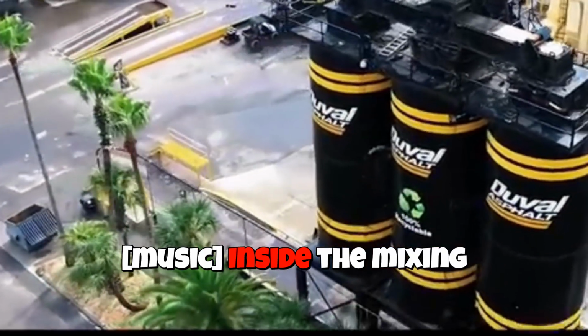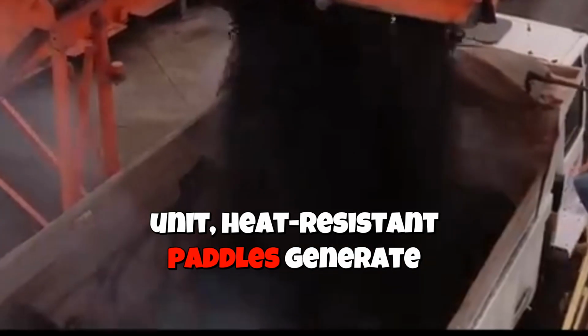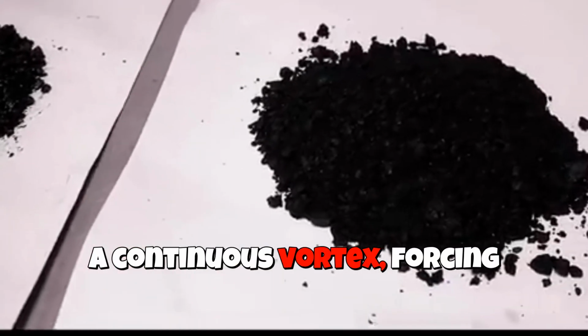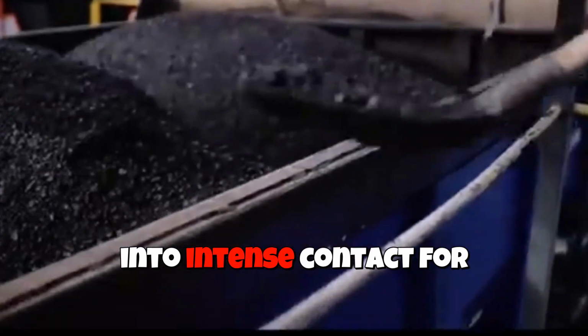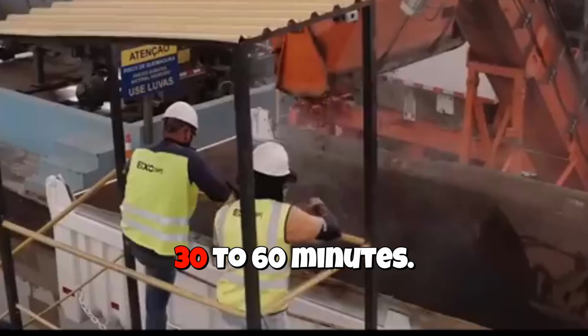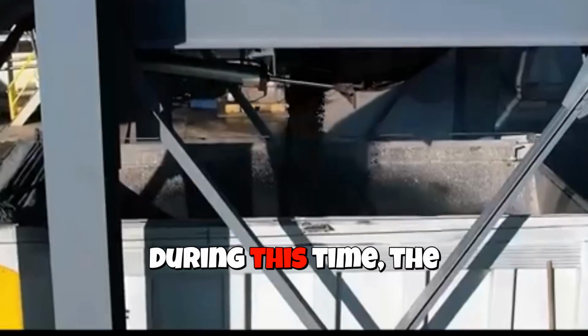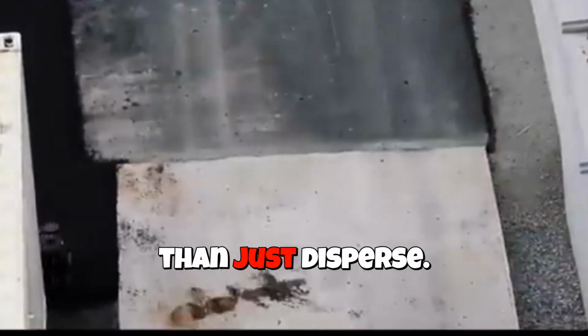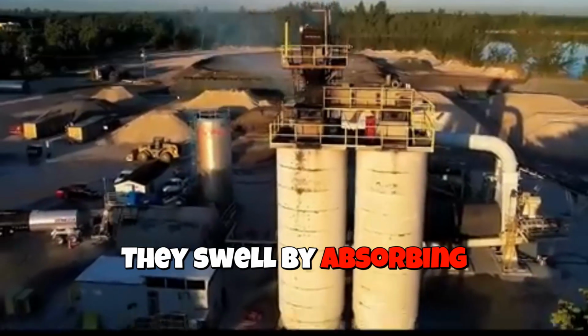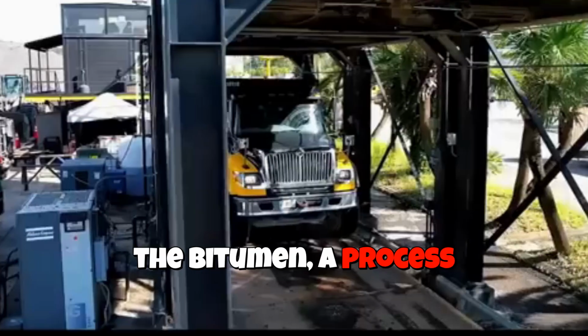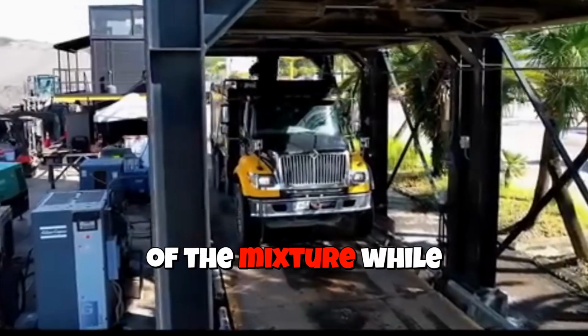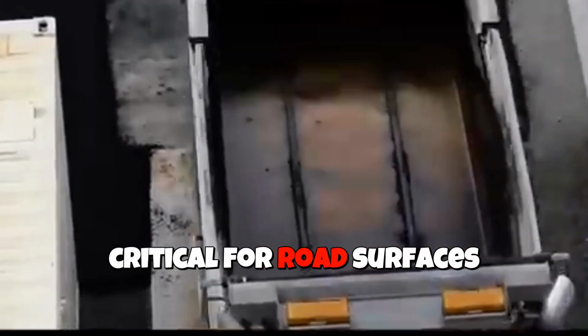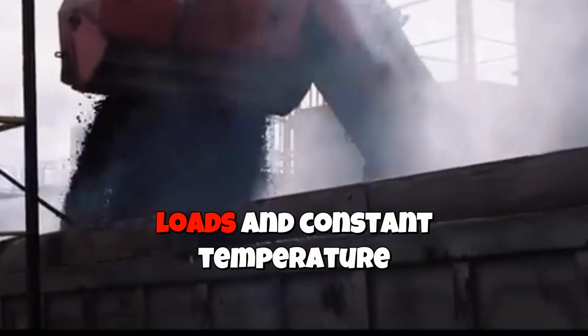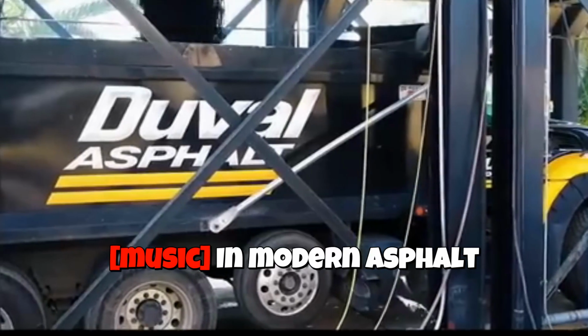Inside the mixing unit, heat-resistant paddles generate a continuous vortex, forcing the rubber and bitumen into intense contact for a sustained period of 30 to 60 minutes. During this time, the rubber particles do more than just disperse. They swell by absorbing the lighter oils from the bitumen, a process that increases the viscosity of the mixture while significantly improving elasticity and crack resistance. These properties are particularly critical for road surfaces exposed to heavy traffic loads and constant temperature fluctuations.